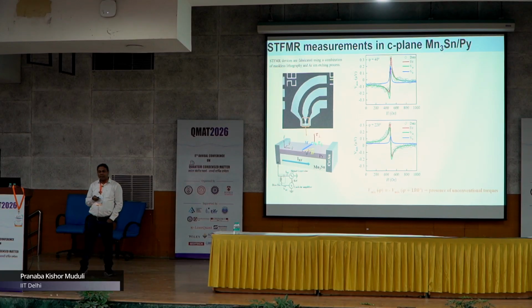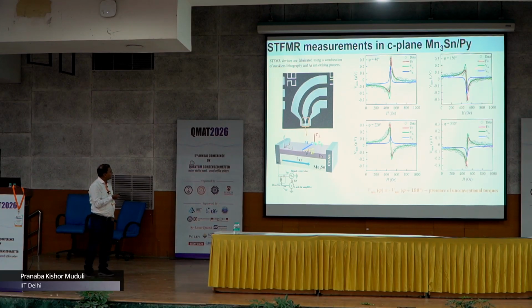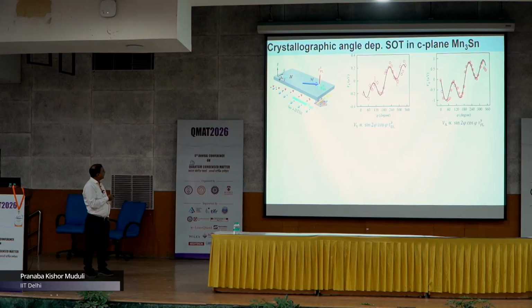We also verified this at another angle such as here, and we then did it as a function of the complete in plane angle. In this case the RF current is perpendicular to the octopole moment, so we do not expect any out of plane current to be generated. Here we saw that the symmetric and the antisymmetric components follow this sin 2phi cos phi dependence. This is the standard dependence that you normally observe in platinum and tantalum, indicating that you are generating a conventional SOT.